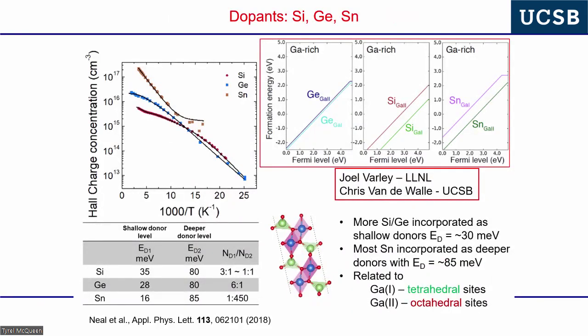You see it because you get two slopes. Quite often in the Arrhenius plots you see two slopes, and that is a hint that when you go to the charge neutrality equation for fitting, these numbers are all fitted to the charge neutrality equation, which includes full carrier statistics, you'll see two donor sites with different occupancies. Okay. Stop there. Thanks.